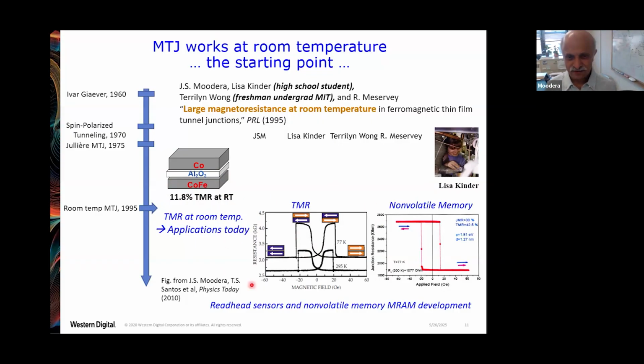So what we have here is the resistance of this kind of structure that may change in the current, in going from parallel state to anti-parallel state. In parallel state, you have large current, that means the resistance is low for a given voltage. And then you reverse the magnetization, you have anti-parallel state, whether you're on the positive side or negative side, the same thing, you have large resistance. Now, on the other side again, once you align them parallel once more, you have a low resistance. That means the current is much larger. So this is what we discovered in 1995.